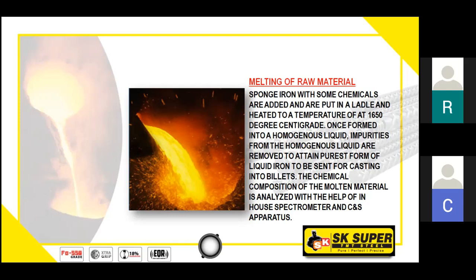All put together, there are 28 different types of alloying elements present in iron, out of which 3 are most important: carbon, sulfur, and phosphorus. This I'll discuss at a later stage. So first, at the raw material stage, the chemistry of the raw material is checked and ensured that it is as per the requirement. If in that 5 kg furnace there is a small bit of variation in the chemistry we intend to have, then by adding some alloys, we get the perfect chemistry.